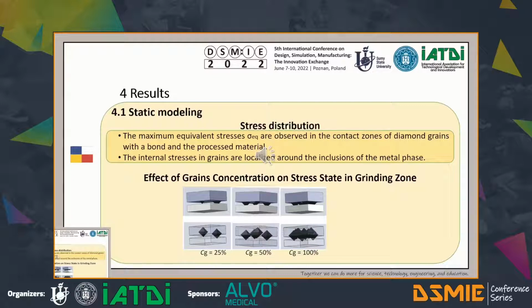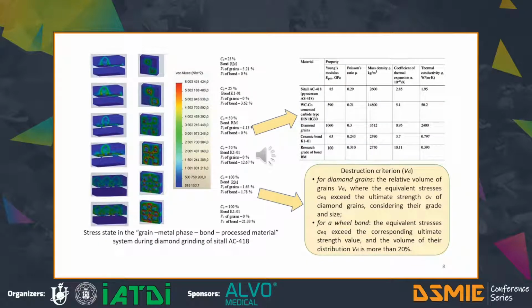It is shown that the maximum equivalent stresses are observed in contact zones of diamond grains with the bond and the processed material. Stresses in diamond grains are localized mainly around the metal phase. As criteria for the controlled destruction of the elements of the diamond wheel, the following were chosen. For diamond grains, the relative volume of grains where the equivalent stresses exceed the ultimate tensile strength of diamond grains, considering their grade and size. For a wheel bond, the equivalent stresses exceed the corresponding ultimate strength value, and the volume of their distribution is more than 20%.